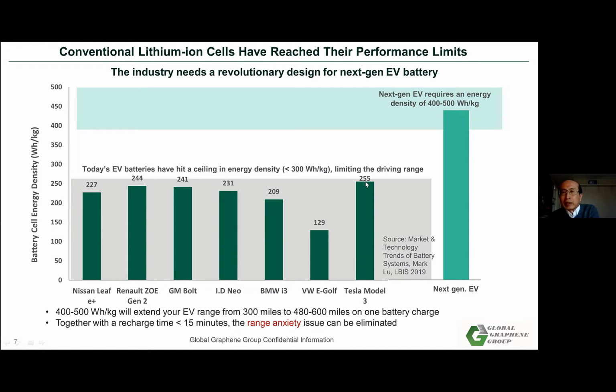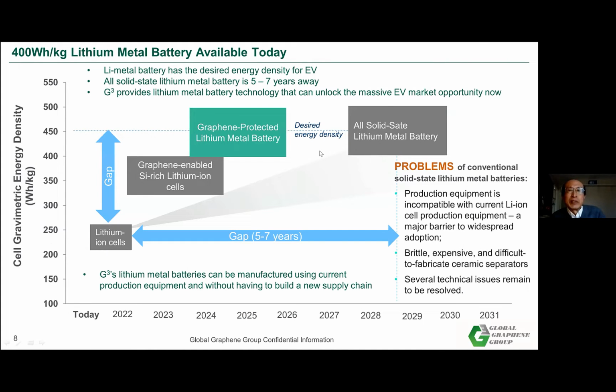The industry is looking to extend the EV driving range by increasing the energy density, and we can achieve that. And here at Global Graphene Group, for over the last 15 years or so, we have stayed focused on the energy applications of our graphene. And for EV battery application, we have been working on the so-called graphene-enabled silicon-rich lithium-ion cells and also graphene-protected lithium metal batteries. Okay, and our lithium metal battery can be manufactured using the current lithium-ion production equipment without having to build a new supply chain.